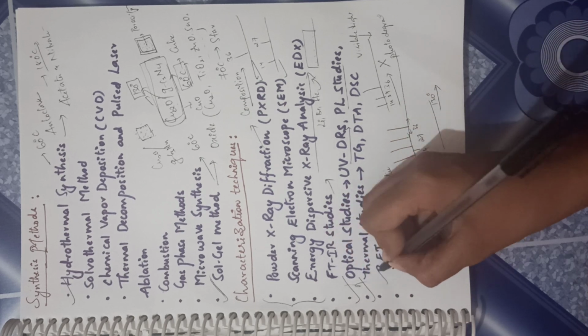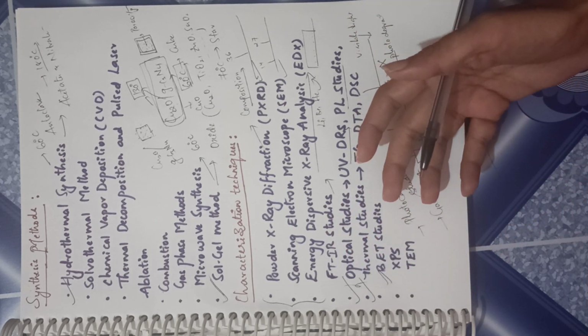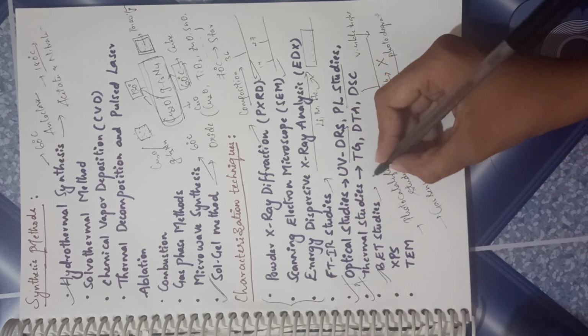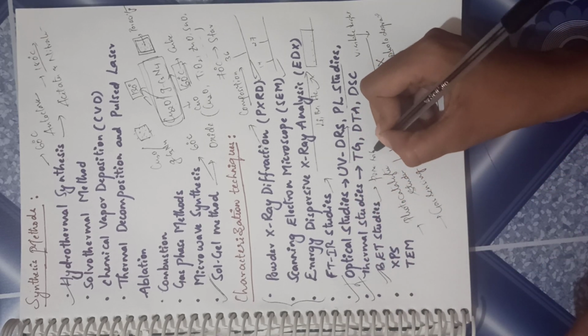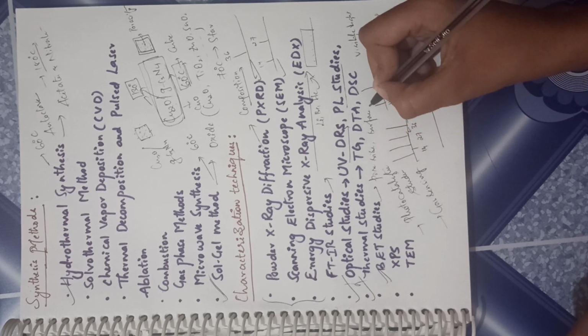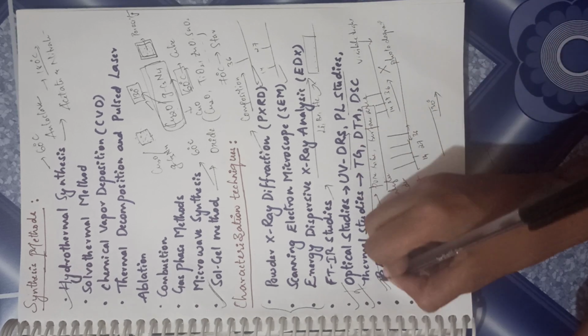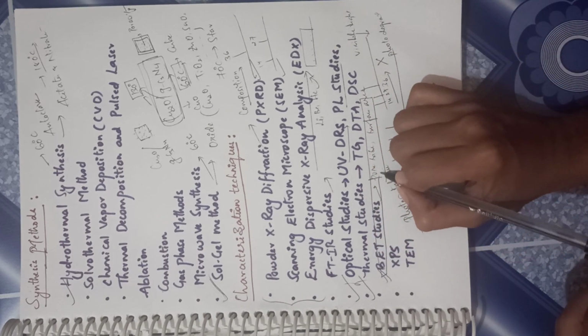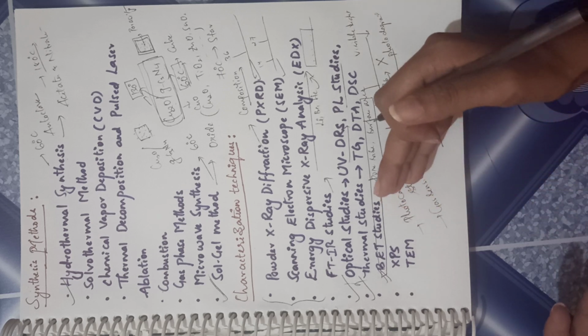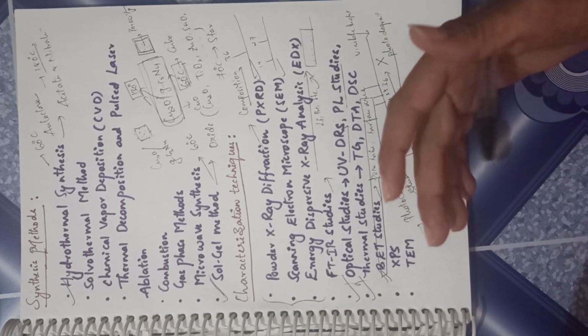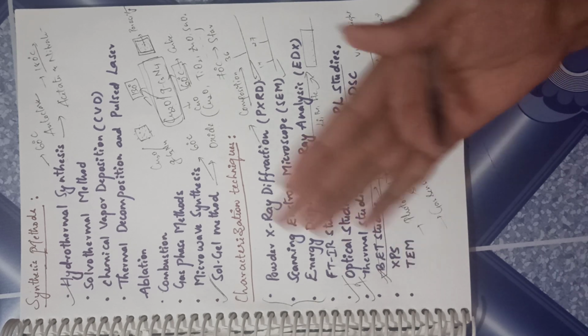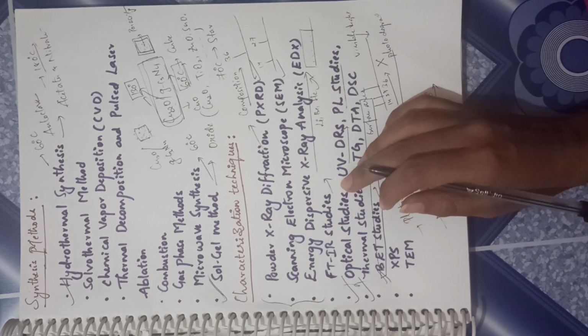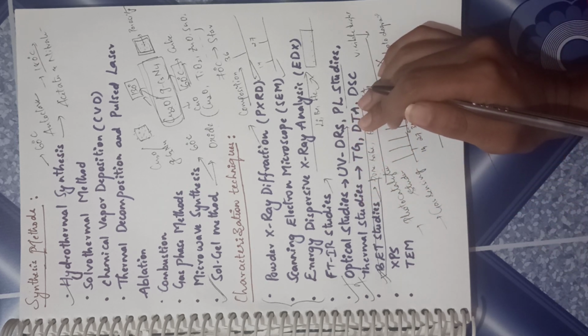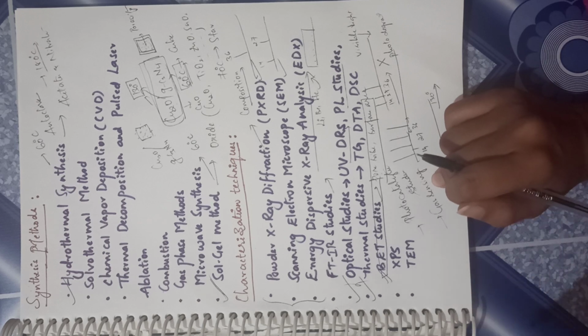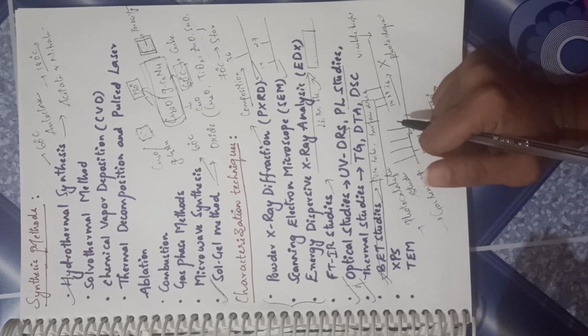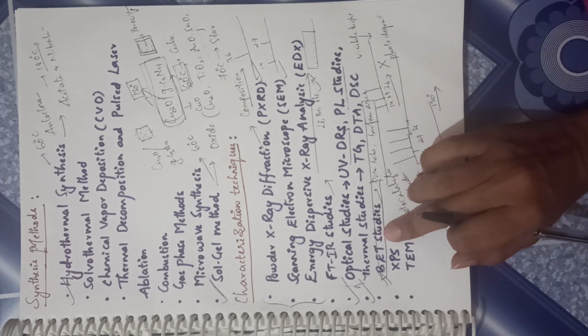Apart from these two, there is a technique called BET. This we have already studied, Brunauer, Emmett and Teller studies. This will give us the pore size of the material. Pore size and surface area can be determined using these studies. Now this is a very important characterization technique which has to be performed, because for applications like photocatalysis and gas sensing, the more is the surface area of the material, the better are the properties of the material. The high activity of the material depends upon the high surface area, let it be photocatalysis or gas sensing. So you determine that surface area as well as the pore size of the material using your BET studies.